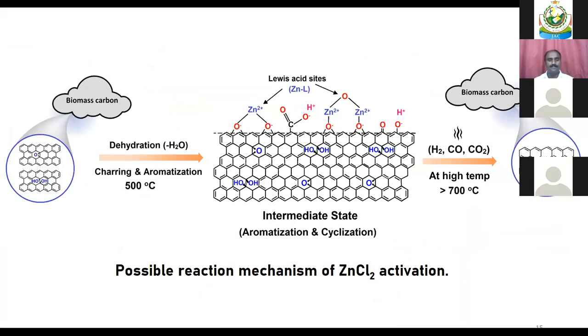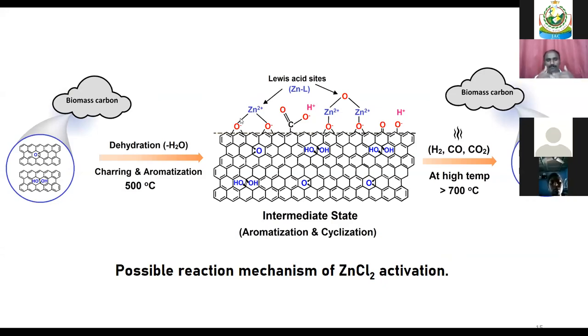And zinc chloride activation. So what is the possible reaction mechanism for zinc chloride activation? You can see we collect the biomass carbon. It's only the carbon lattice. At a particular temperature, we have the aromatization heating. It goes to charring or aromatization. That means the carbon layers are connected together, and then the zinc chloride is deposited on the surface. It will interact with the zinc 2 plus and the oxygen atoms, and finally we get the zinc oxide. And this zinc oxide is removed by using concentrated HCl as zinc chloride. Finally, we get the porous activated carbon.